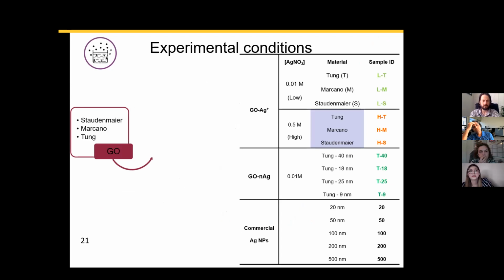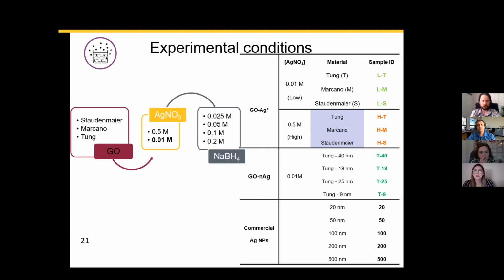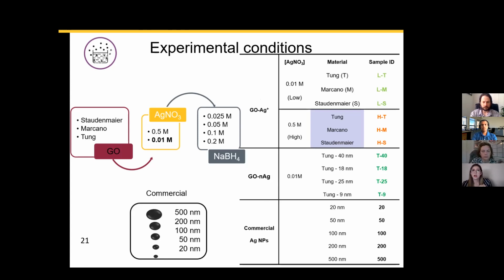We have different experimental conditions, and we started by working with 3 different types of graphene oxides. These are all very structurally different. The names come from the synthesis methods that were used, and basically the main difference is that they have different extents of oxidation. Staudenmaier is a very reduced graphene oxide, whereas Tung is a very oxidized graphene oxide. And we wanted to synthesize the silver nanoparticles in situ. So we used a salt precursor, namely silver nitrate, and we reduced these particles by using different concentrations of sodium borohydride. So we have composites with graphene oxide and silver salt, and graphene oxide and silver nanoparticles of different sizes, but we also wanted to see if we actually needed the graphene or the carbon support on this composite. So we tested commercial nanoparticles of different sizes to see if there's actually a size-dependent effect for bromide removal.